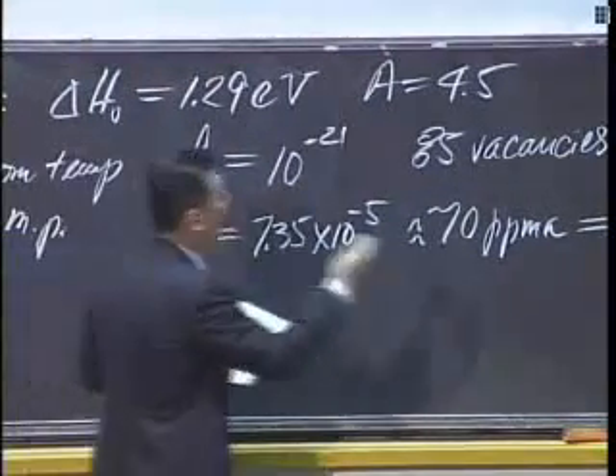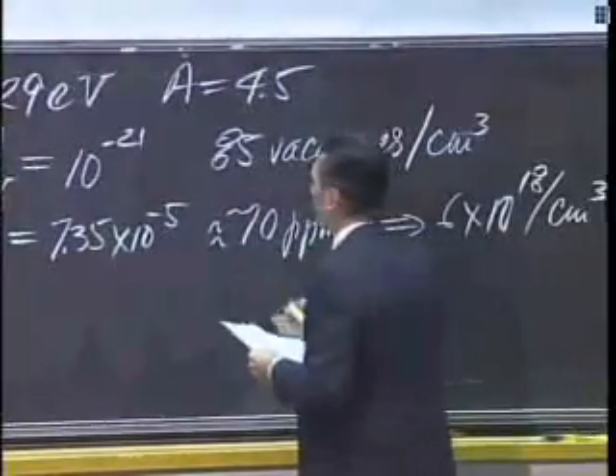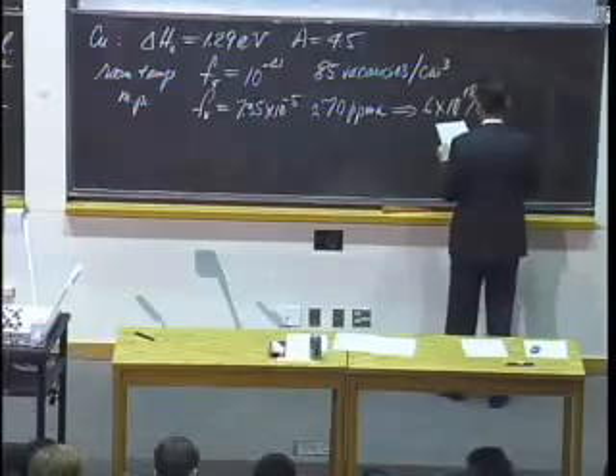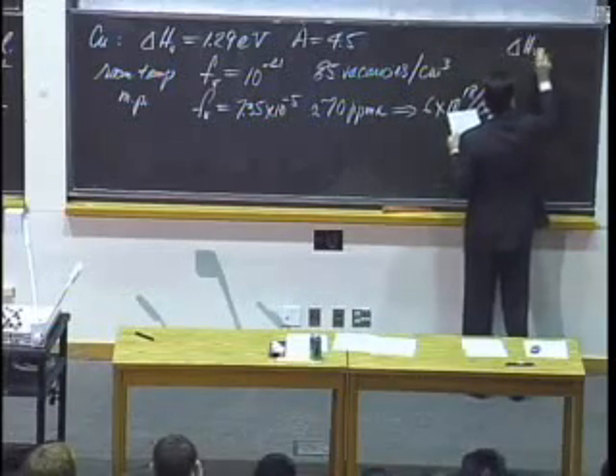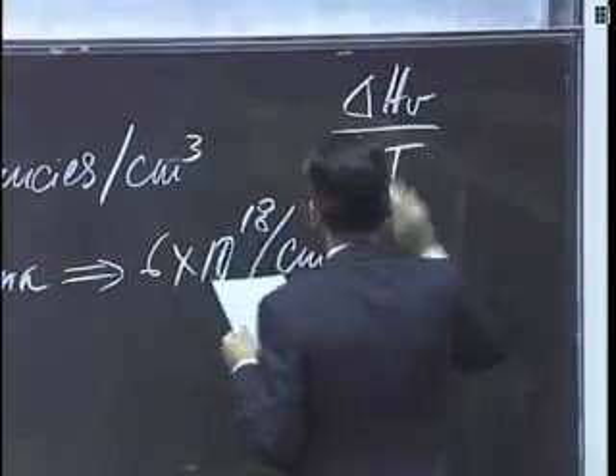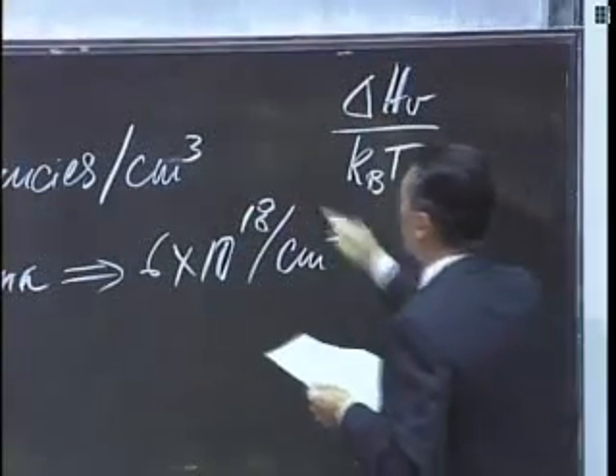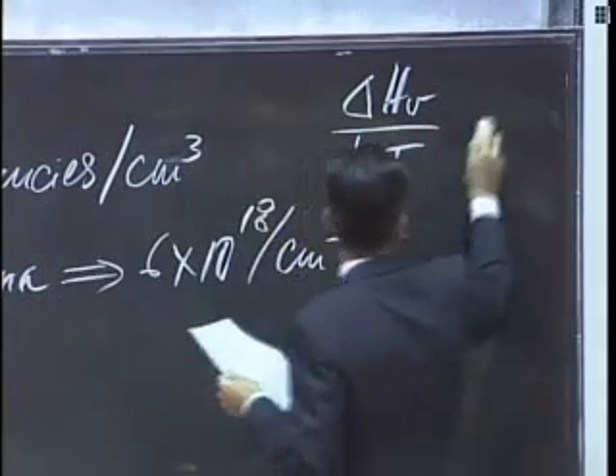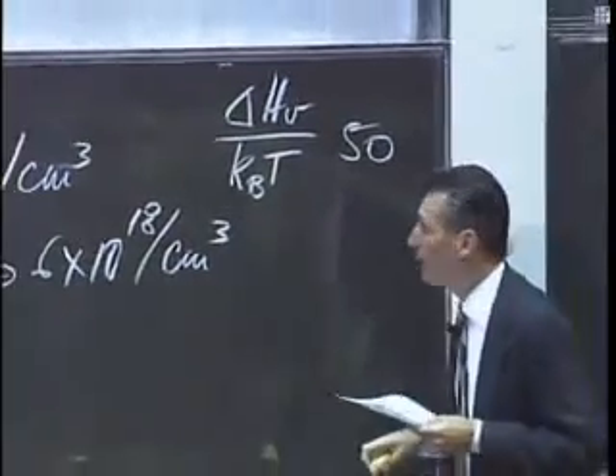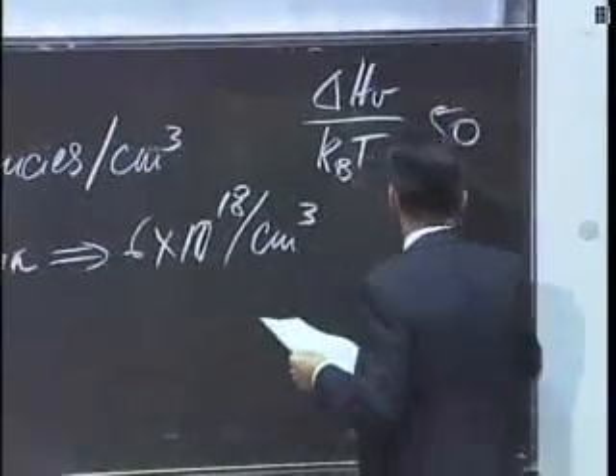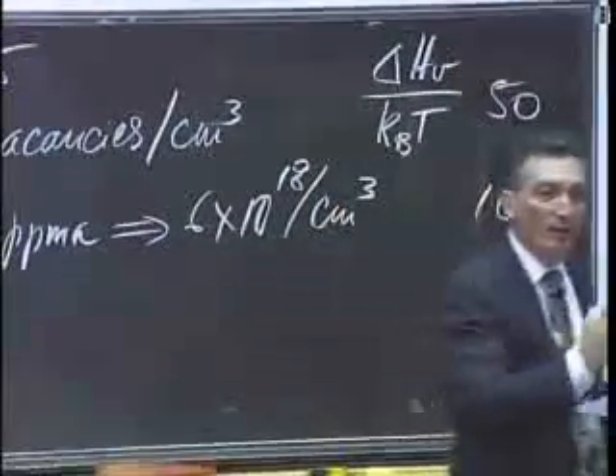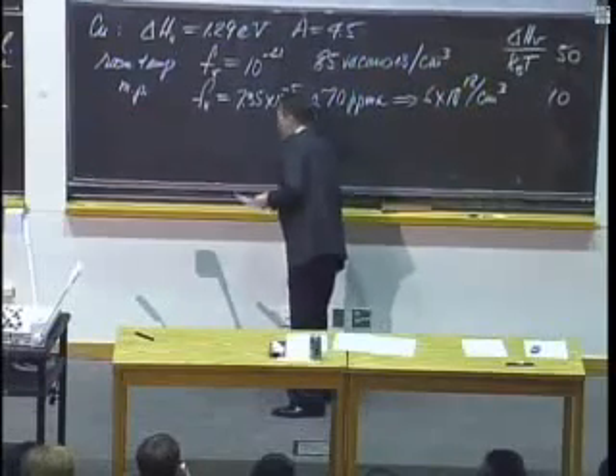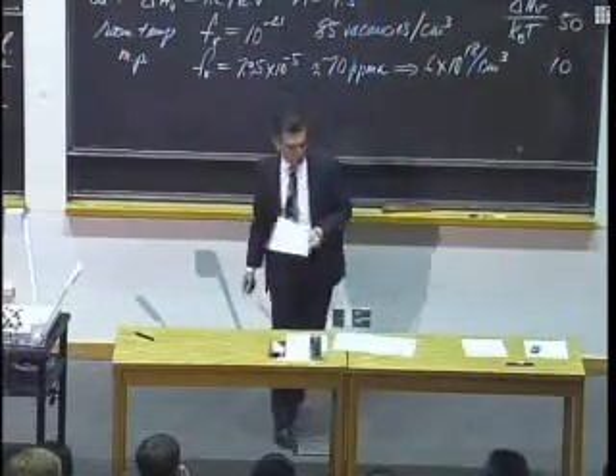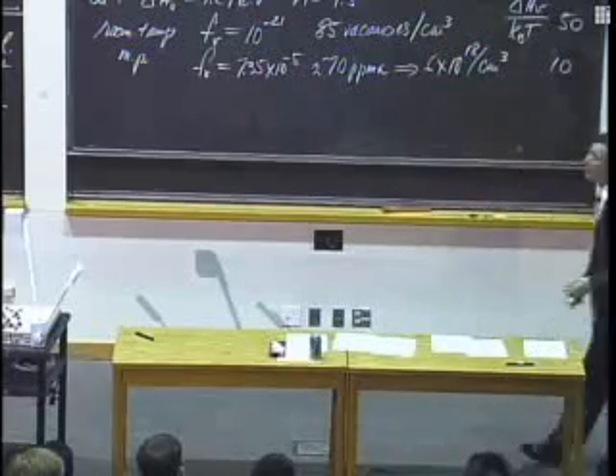And here's the way to look at this. What's going on here is this critical ratio. This is so important. The ratio of the binding energy to the thermal energy. At room temperature, this ratio is about 50 to 1. At the melting point, it's about 10 to 1. And that's what's going on. You're shifting the distribution way over and giving yourself the ability to rip the copper atoms out of their sites. So that's interesting to know.